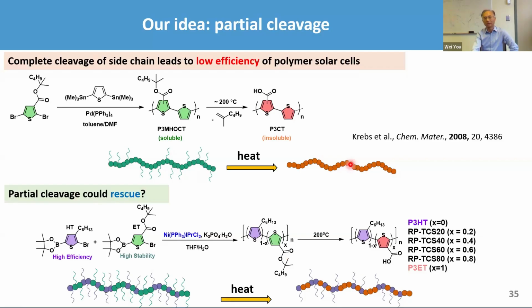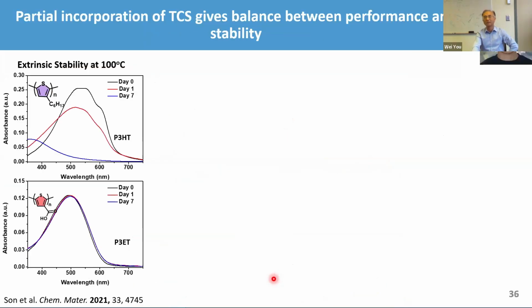So what we were thinking is, perhaps we can try partial side chain cleavage, because you possibly need some of the side chain for morphological control. But you also want to remove a lot of the other side chains, because you want to increase the mobility and also carrier concentration and many other good features associated with side-chain-free polymers. So essentially, we're mixing the side-chain-free polymer with the side-chain-decorated polymer in a chemical blend, if that makes sense to you.